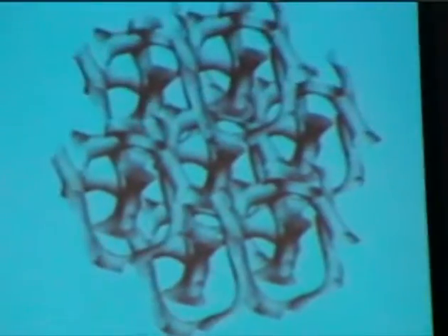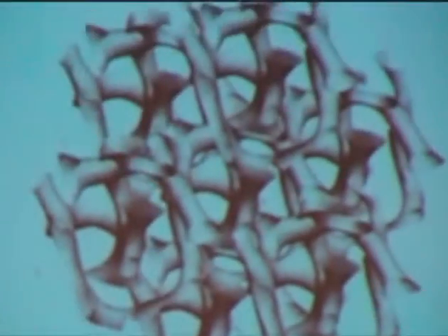And a third possibility that's used a lot, and is maybe more important for catalysis ultimately, is a cubic structure. So in this kind of structure, I'm just showing where the pores would be actually in this kind of network, but it is a periodic structure, and you have actually three-dimensional connections between the pores. So this example that I'm showing here is called the gyroid phase sometimes, which is the mathematical description of the surface that divides the inorganic and organic parts of the original structure. But there are other types of cubic structures that can be made.